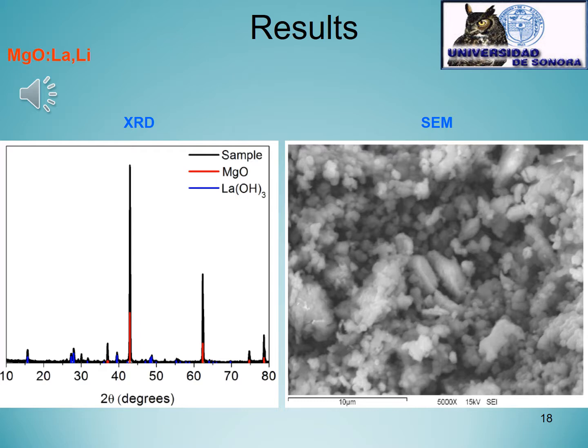Another novel material that we could obtain is magnesium oxide, but now lanthanum and lithium doped. In this case, for the XRD analysis, we can observe the mixture of two crystalline structures or phases corresponding to magnesium oxide and lanthanum hydroxide.